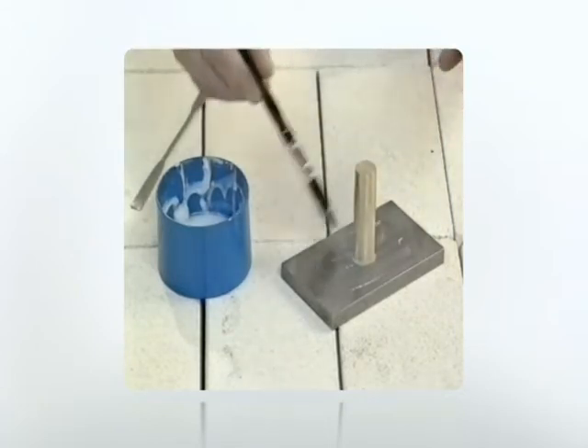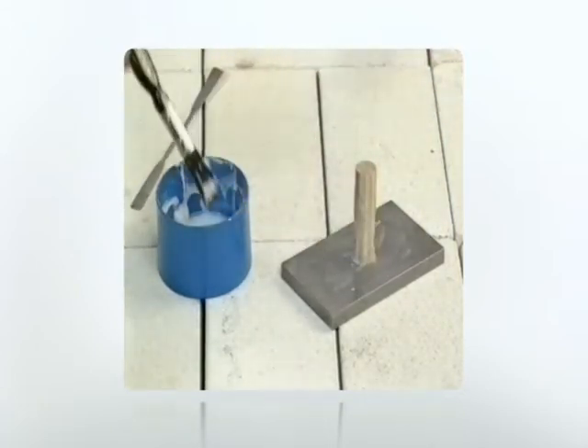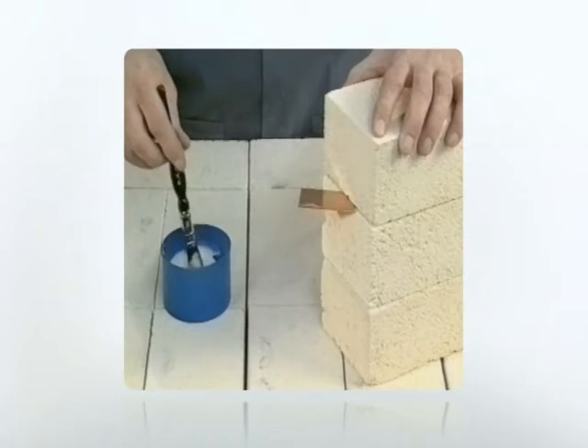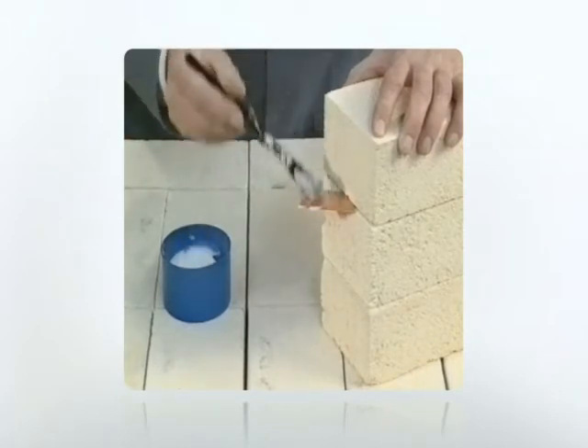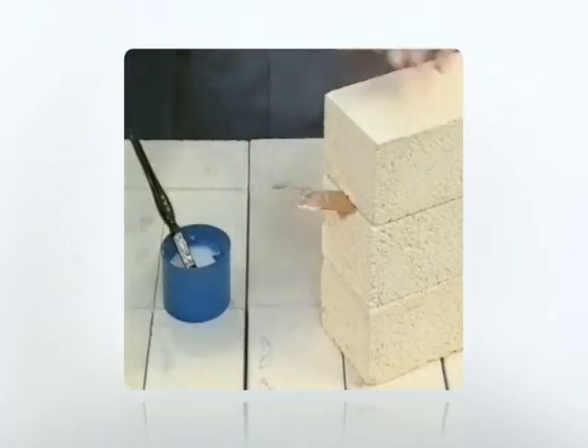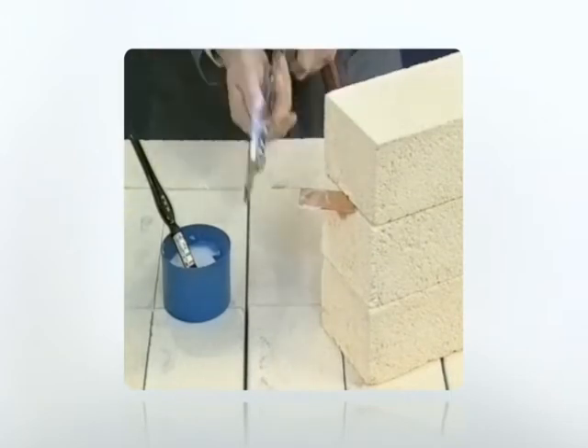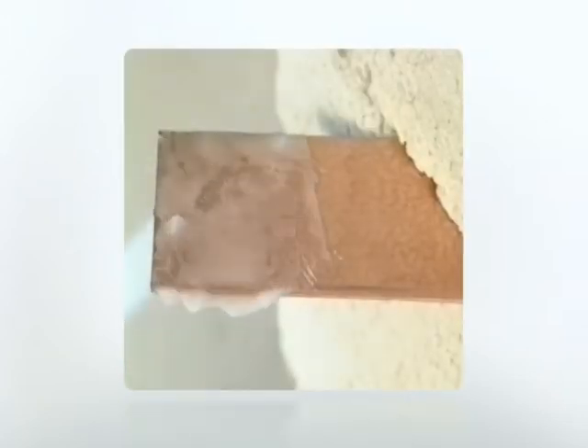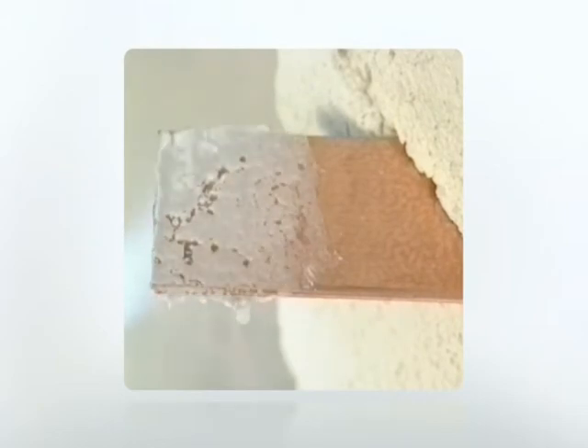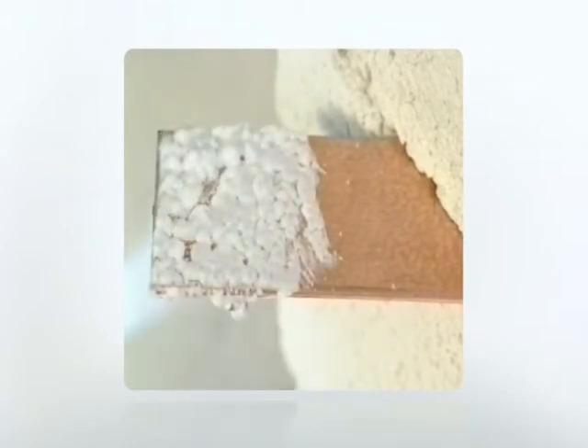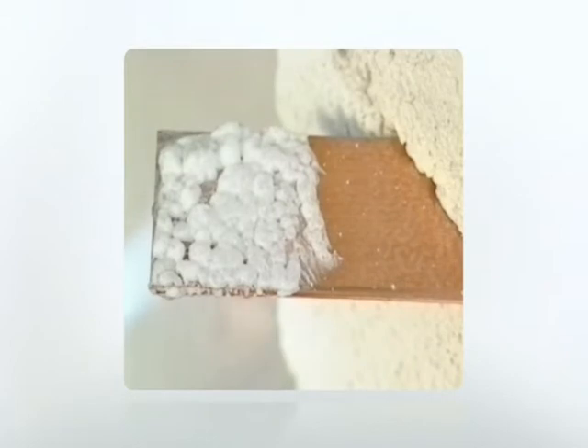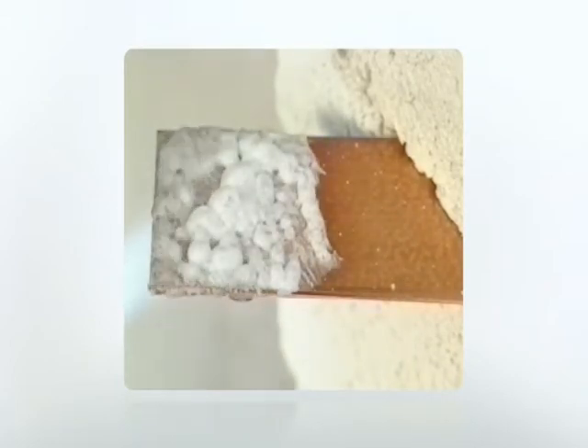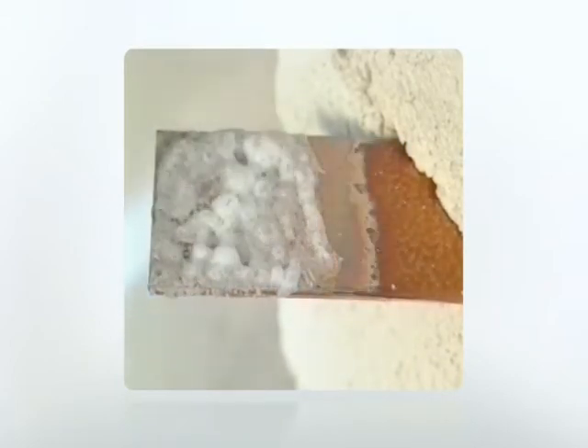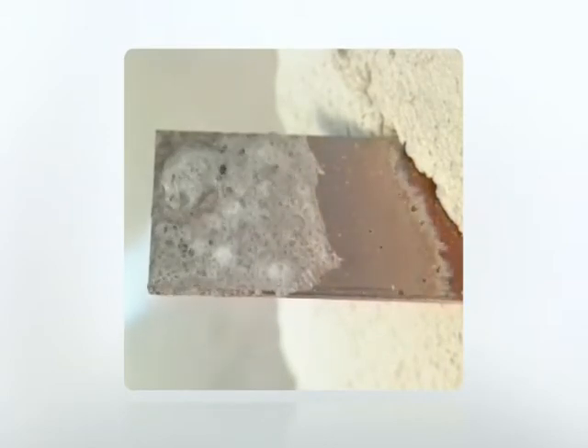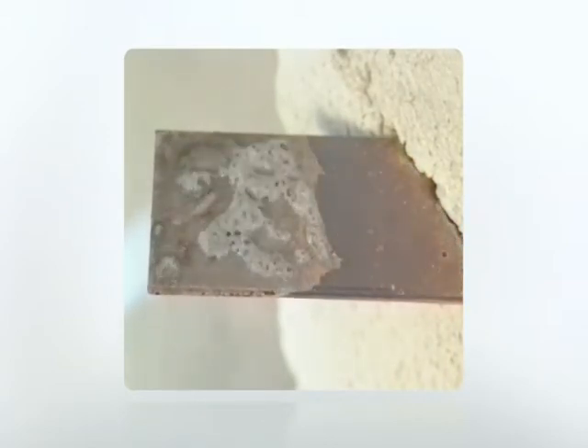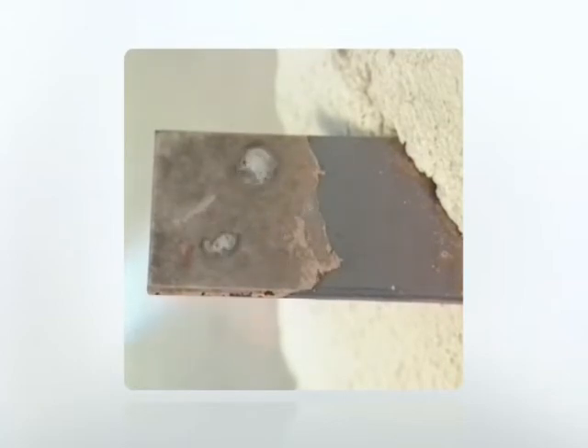The flux also serves as a temperature indicator. This can be demonstrated with this copper plate, which is first fluxed and then heated. At 100 degrees centigrade, the water boils off. At around 300 degrees, the flux begins to turn white and puffy. It's now active and protecting the metal surfaces. At about 600 degrees, the flux becomes clear and runs like water. This indicates that the brazing temperature has been reached.